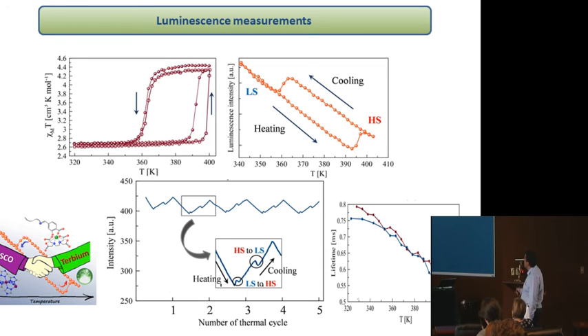If you cycle the composite several times, we have a similar response. The fluorescence is stable, so you have good stability. So you have detection again and stability because of the presence of the terbium. The fluorescence of terbium is more stable than organic materials. Now, if you look again at the fluorescence lifetime, you have no effect of the spin crossover state. So this corresponds to a radiative energy transfer. So you have an emission and a reabsorption of the photons. Okay, so we are finished.